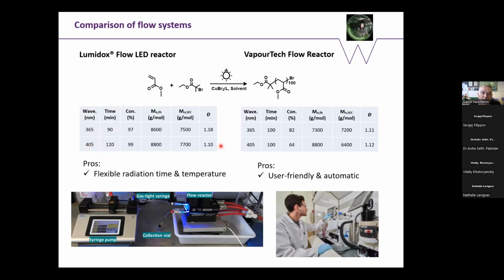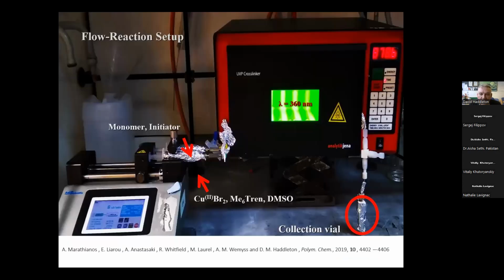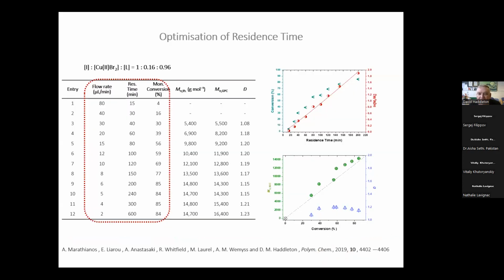Dispersities less than 1.20. And if we use the scale up, the Vapourtec, this machine here, we can get, well, spot on molecular weights, so really spot on, and we can get very good dispersities. We can also do it in this type of thing, which is normally used by biochemists to do cross-linking, and we just flow it around there. And from that reactor, we will get these dispersities, and you can change the residence time, the flow rate, etc. And so very easy to translate between flow systems and very easy to do this by photochemistry.